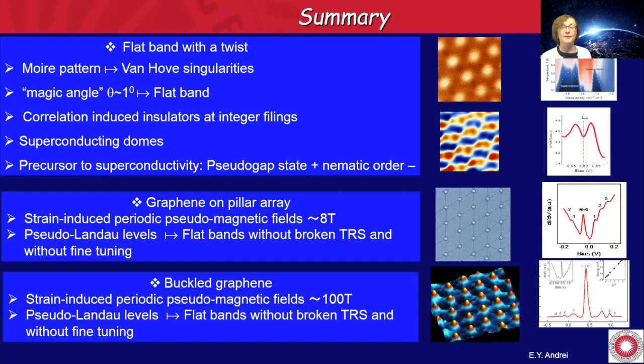Now, we are also able to put the graphene on an array of pillars, which enabled controlled stretching of the system and controlled application of strain, and that gave rise to a pseudomagnetic field. And the same thing happens when you have naturally buckled graphene, where we see pseudomagnetic field that can be as high as 100 Tesla, giving rise to flat bands without breaking time reversal symmetry.